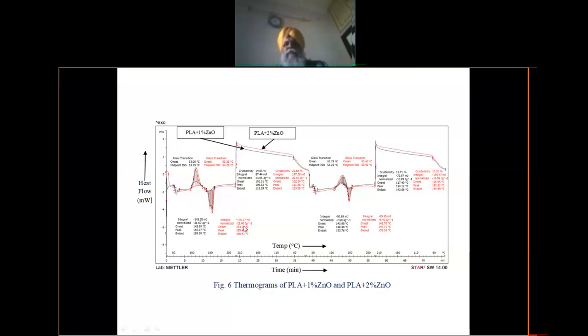But we want to see whether with this reinforcement, the energy absorbed in each heating and cooling cycle remains the same, or it is going to vary in the successive cycle. What we observed is for these types of polymers, once we have these types of smart materials, for 3 to 4 cycles, the material is stable, but after four cycles, the material is going to behave in a different way. So we have to think which particular composition is going to give me this type of material in a more stable manner in the heating up and cooling cycle.